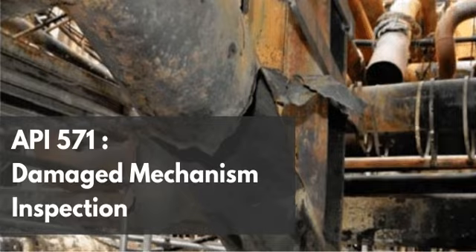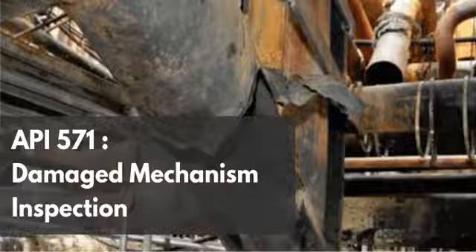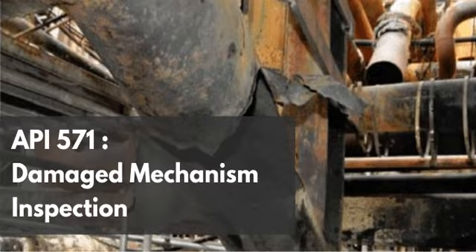Okay, so if this damage is eating through half this wall thickness, specifically hidden inside the pipe, localized at the welds, how do inspectors actually find it before the pipe completely ruptures? We can't just cut the plant apart to look inside. This brings us to the critical realm of in situ inspection and damage detection. Finding this localized damage is arguably one of the greatest challenges detailed in the inspection protocols for these units. Because it's so localized, right.